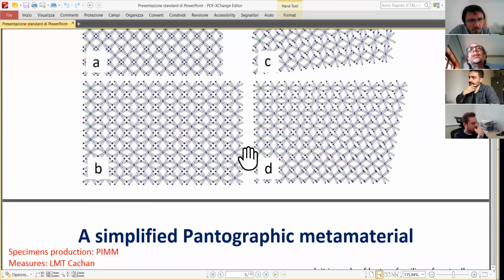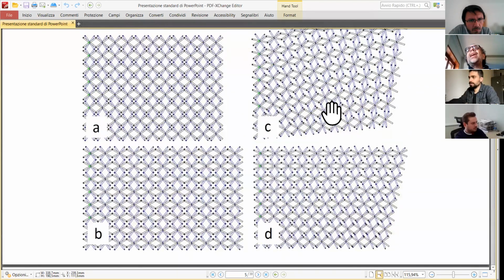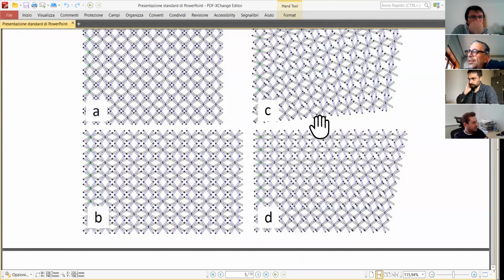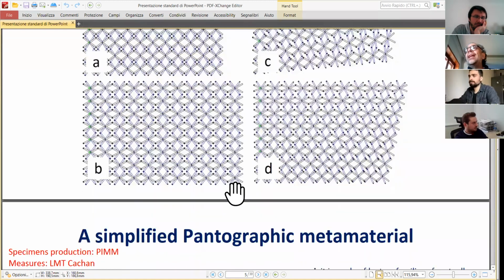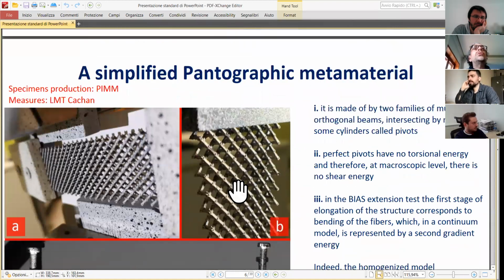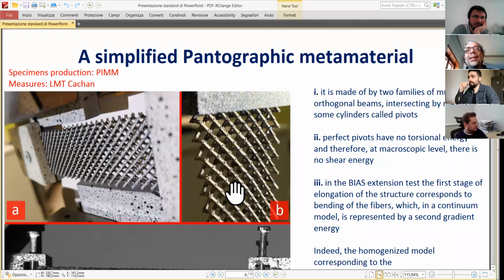And this bipantographic sheet has a homogeneous deformation in the plane, if the pivots are perfect, which is totally energy free. So in a sense, they are what mechanical engineers call a machine, because you have degrees of freedom and the system is changing without a lot of deformation energy from one configuration to another among the allowed ones. Once you homogenize this material and you add a small deformation energy related to the shear deformation, then this becomes something which can be used in large deformation, remaining elastic in large deformations.